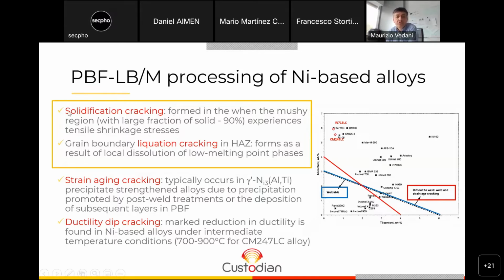But also of importance, playing a very important role, is grain boundary liquation cracking, which is not exactly related to the solidification mechanism. It takes place in the already solidified material due to the thermal cycles, due to the intense heating which is produced by either the heat affected zone of the welds or during the solidification of the following layers in the powder bed fusion process.